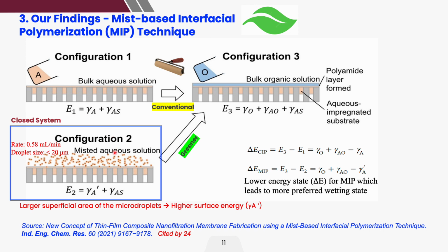For the MIP technique, instead of pouring the solution on the membrane's surface, we introduce small droplets of water on the membrane surface. These droplets typically are less than 20 micrometers in size. Because the size of the water droplets is very small, it gives a very large superficial area, and this eventually leads to higher surface energy and makes the surface of the membrane have a higher degree of wetting.